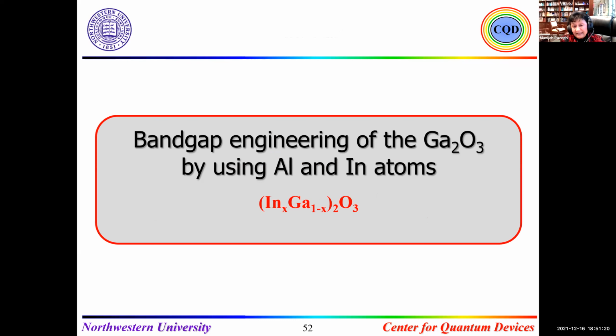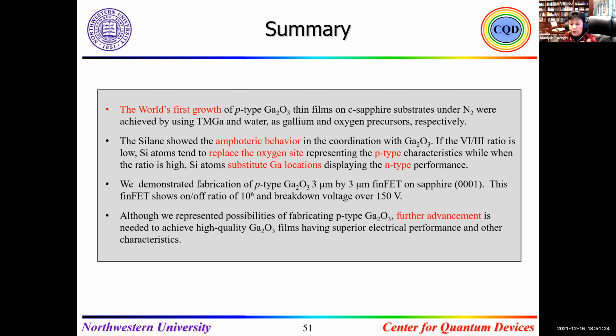And when we did that, another problem - we gave it to Professor George Schatz, who is an excellent theoretician at Northwestern, and I asked his group to work on demonstrating this. They demonstrated that by doping with silicon, the alpha phase is much more adapted for p-type, and that there's a vacancy of gallium coming with hydrogen, and at the same time giving p-type by substituting silicon for oxygen. So that paper also came out, and if you have a question I can show you later.